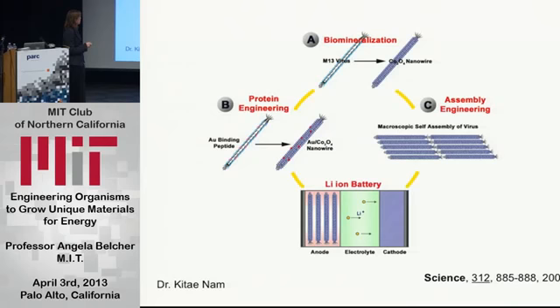But we used a combination of selection and rational design to try to make them better as a function of time. And I always say that's one of the things I like best about working on our technology is that you may start out with 1 billion possibilities, and you're looking for a virus that can do something, grow a material, say in this case cobalt oxide.